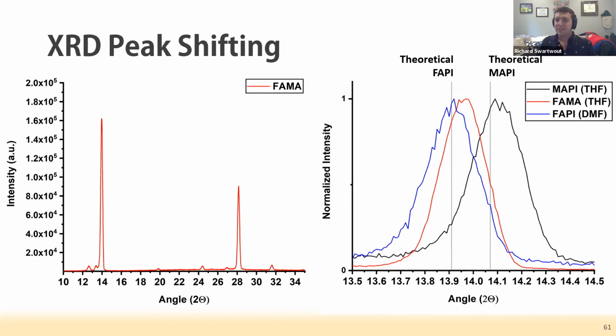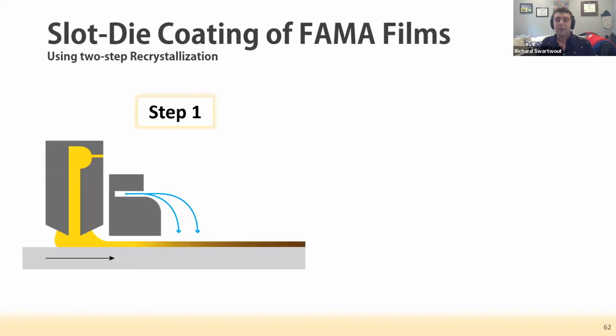Of course, this is great on small scale, but we're really looking at translatability here. So for slot die coating, this process was also translated. The first step, again, this is a 2-step process—I've already shown it's a slot die coated ink with an air knife drying method to make a methylammonium lead iodide film.